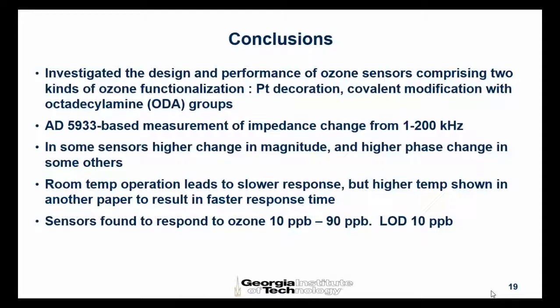Room temperature operation gave too slow a response, but yesterday I presented a paper where we showed that with 75 degrees heating, we put a small heater next to the sensor and heat it to 75 degrees, we could reduce the desorption time from 90 minutes to about 30 minutes.